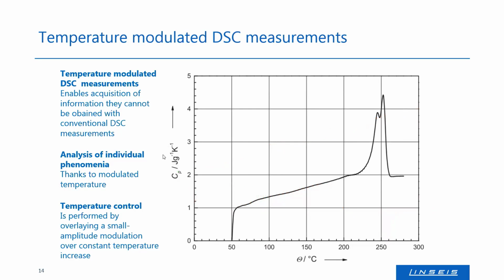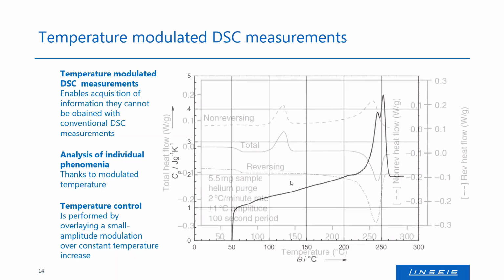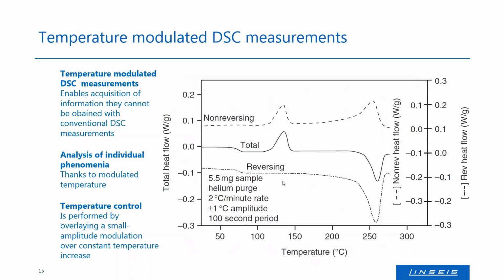So this is now a literature value for a CP of a polymer. And what could we see here for the CP? Okay, it's rising. And then there's a small step at around about 70 up to 80 degrees. Then it's still rising, and then we have the peak here. I think it's the melting peak, so I can tell you this is the melting peak. And then it goes on at a bit lower level here, but then it will rise again. So, okay, this is the literature. But there's some more information we could get through the temperature modulation.